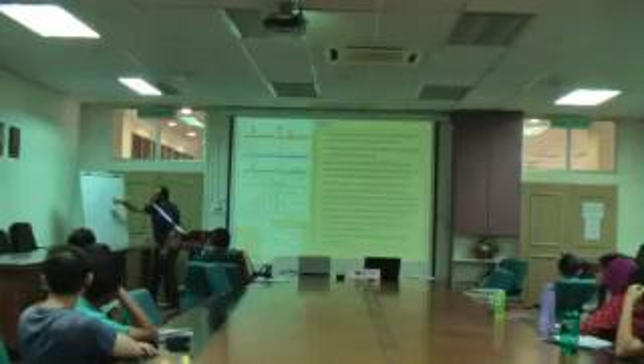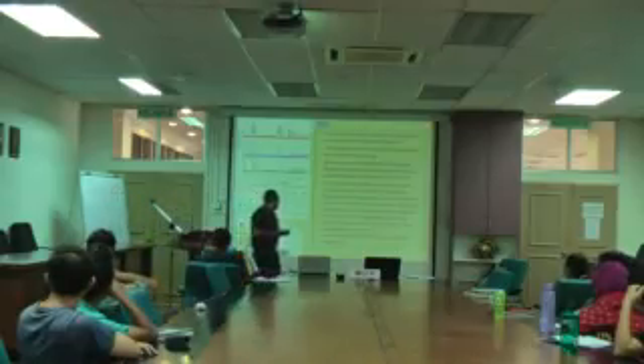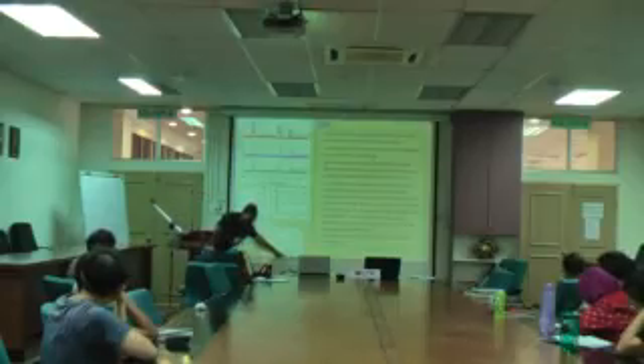In mathematics it's very easy. If this is y, this is x, this y-intercept is this one, and the slope is this one. If we compare these two, that means K lambda over D is the y-intercept and 4 epsilon is the slope. That means sine theta is x, beta experimental cosine theta is y. So this is the Scherrer formula and this is the Williamson-Hall formula. If we plot beta experimental cosine theta as a function of 4 sine theta directly, we can calculate strain and size by XRD.